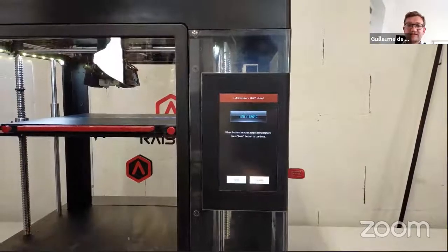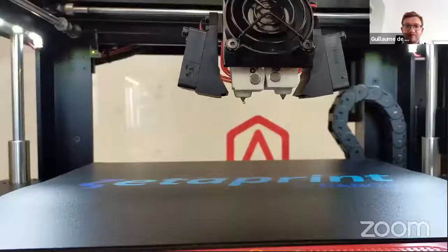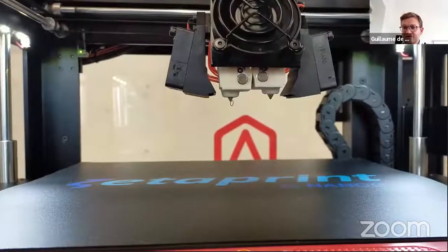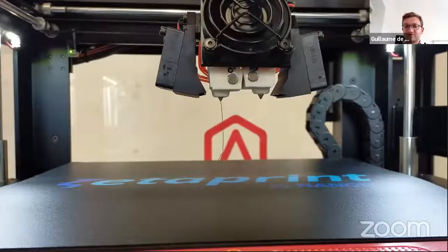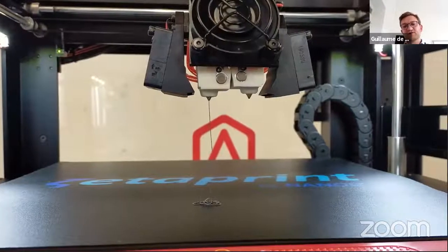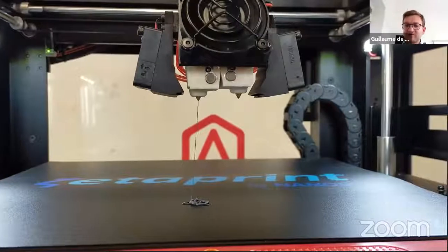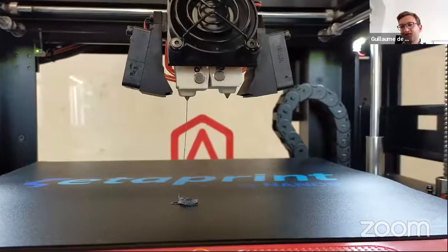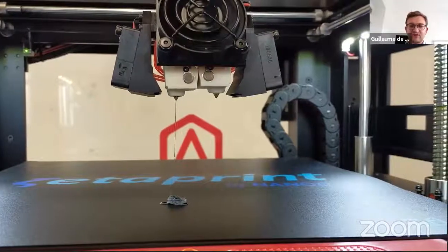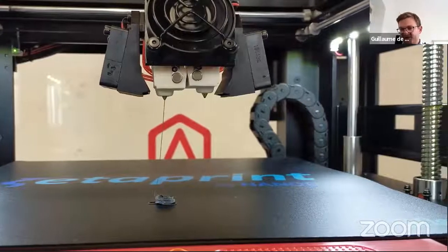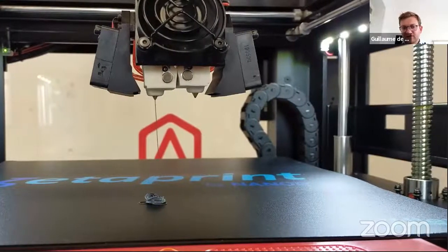So here again, you can see we are preheating the nozzle, and then we will push the filament, and we are going to wait to see a bit of material coming out of the nozzle. We usually wait a bit to make sure that the filament is really primed. There's no more air, any bubbles, anything inside the nozzle, and it's ready to print.